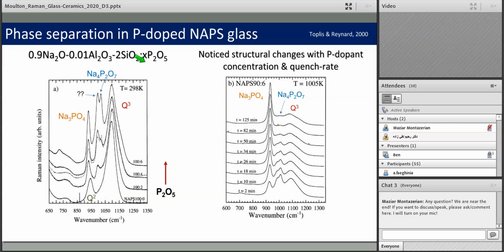Another example is a sodium silicate with a little bit of aluminum and phosphorus added. They noted that there were quite strong structural changes as the amount of phosphorus was added from 2 to 4 to 6%. The bands here grow quite intensely, and the second and third bands grow intensely here. These are related to the formation of orthophosphate and pyrophosphate groups in the melt. Because these have one bridging oxygen and no bridging oxygen, there's evidence to show that there's quite a strong phase separation between the phosphate and silicate networks.